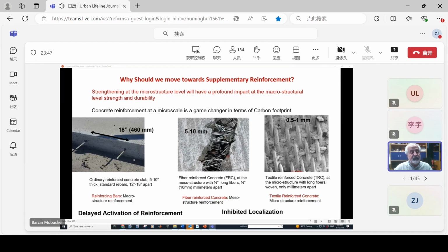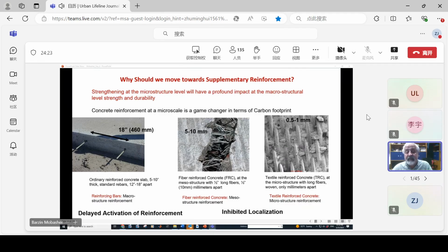And that fracture problem means that we cannot allow all of this concrete to have a crack that propagates all the way through it. We go to fiber reinforced concrete, and we get a tremendous performance out of it because we're reducing the size of reinforcement by almost 1.5 to 2 orders of magnitude. So now the fiber is very much in close proximity. We can go 1 order of magnitude more. Now if you're doing textiles, and these are polymeric textiles with a material that is much lower in stiffness, we get 10 times better performance and improvement in the properties of the concrete that we're using. So in my opinion, going with textile reinforced concrete, we're doing a reinforcement at the microstructural level.